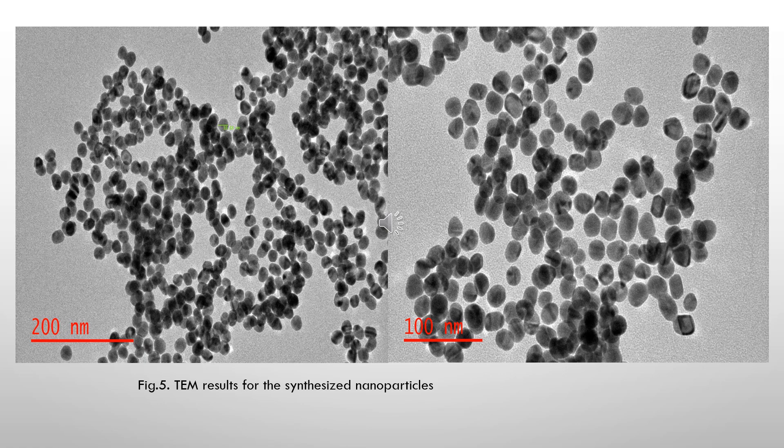Following the X-ray diffraction assessment, we performed transmission electron microscopy analysis of our nanoparticles and were able to see that we obtained spherical nanoparticles approximately 20 nanometers in size, which was deemed good for obtaining a visual readout signal. The whole aim was to attach one of the probes to gold nanoparticles so that the gold nanoparticles could give us a readout signal once they are near to the target gene.